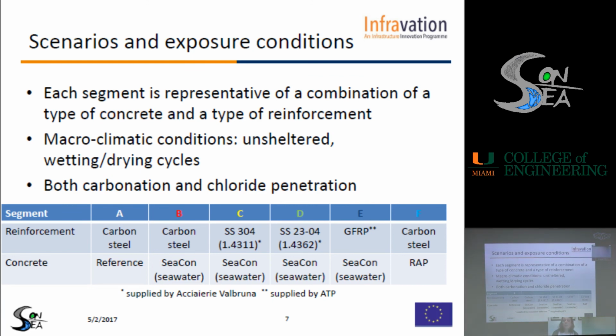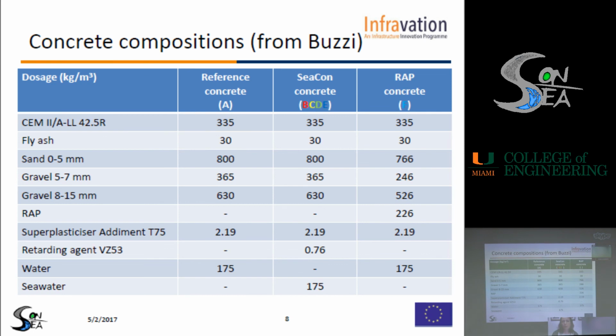And finally, the segment F is made again with carbon steel and RAP concrete. That is a concrete that is obtained by a partial replacement of coarse aggregate with recycled asphalt pavement. The concrete compositions that were designed in agreement with Buzzi are reported in this table.